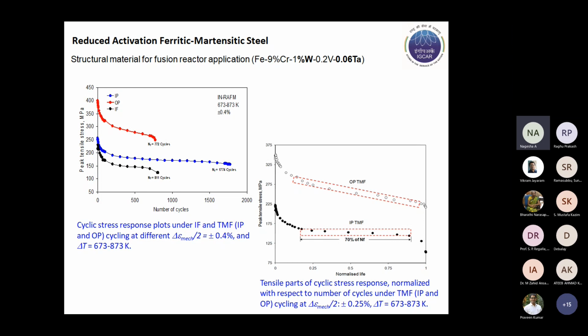As we know, elements such as molybdenum, niobium, etc., give rise to very long-lived isotopes that make the structural materials highly radioactive during operation. So, in order to reduce the long-lived isotope formation, it is normally recommended to replace molybdenum and niobium with low activation elements. Generally these alloying elements are tungsten, vanadium, and tantalum. And here also, in this material, we have done systematic investigations on isothermal and thermomechanical fatigue.